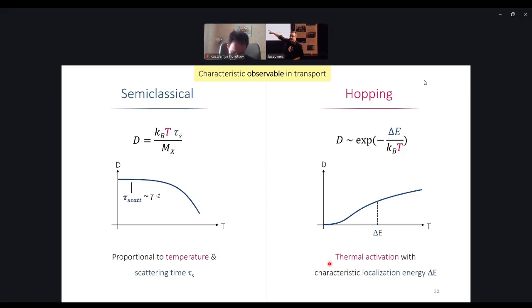What it will mean here, and this you can see sometimes even in very good quantum wells from the 90s, grown by famous people, is that if you go to very low temperature, you will have this behavior, and then at very low temperature this will drop again, but not necessarily because of localization, but because of the scattering. This is very important, so thank you for mentioning this.